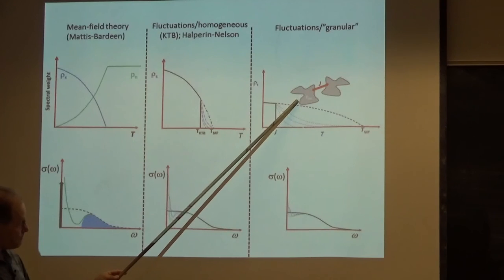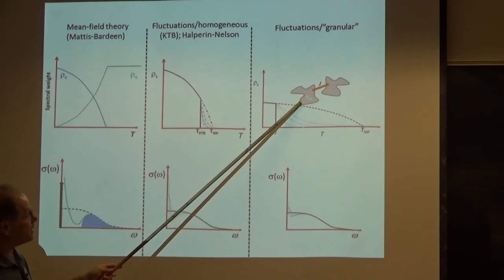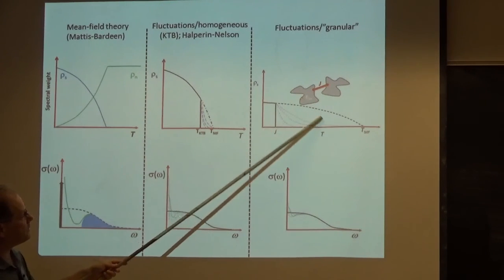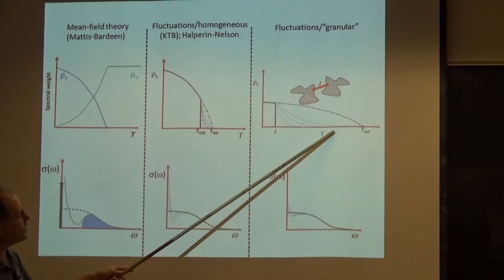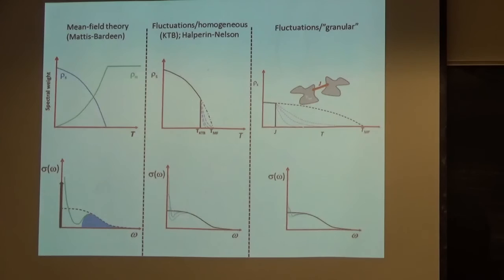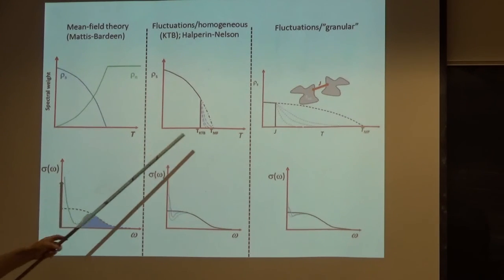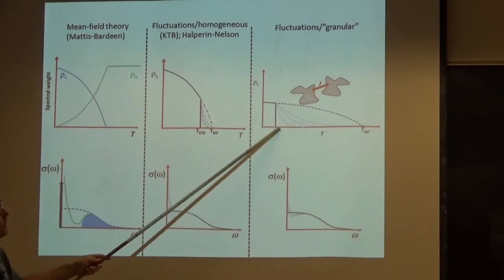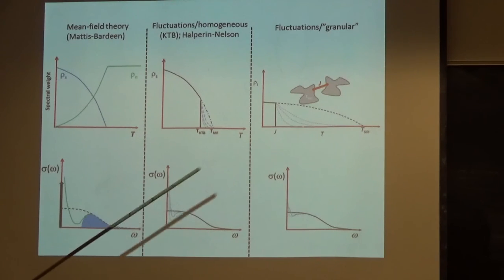You can have an arbitrarily large contrast between the intergranular connection and the mean field temperature, and that will broaden this regime of the vortex plasma to become arbitrarily large. Another interesting case that Steve and his collaborators have worked on is the famous case of LBCO, where you have a frustrated coupling between layers that form a stack. Now instead of a grain here, I have a two-dimensional superconductor, but it has an incredibly weak Josephson coupling to the next layer, also giving me this enormous range of fluctuating superconductivity.